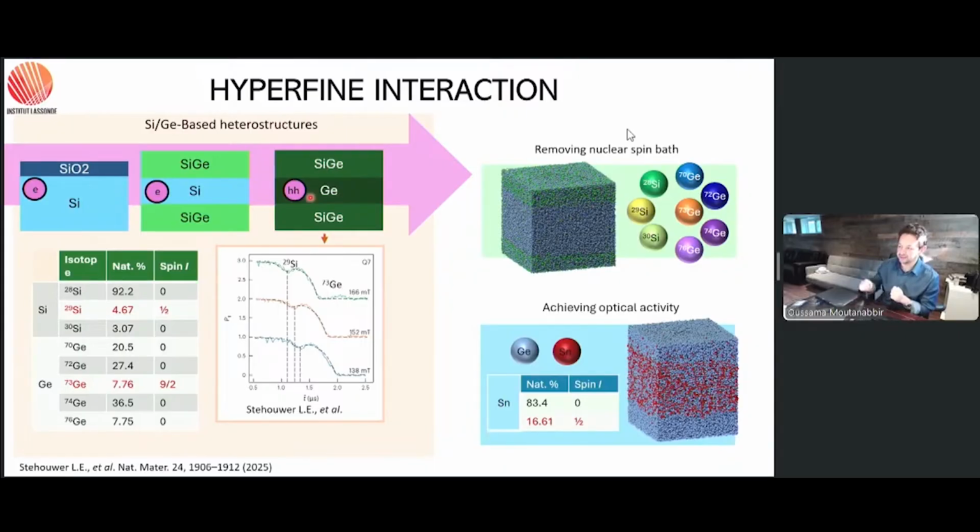In germanium-73, you have a 9/2 nuclear spin, and this spin not only couples to the hole spin, but the orientation of the spin will also impose constraints on the configuration of the magnetic field that you want to use, in plane versus out of plane. So you cannot leverage the g factor anisotropy. That is one of the arguments why hole spin is really interesting. So I'll start by showing you what we are doing in terms of achieving this platform without any nuclear spin.